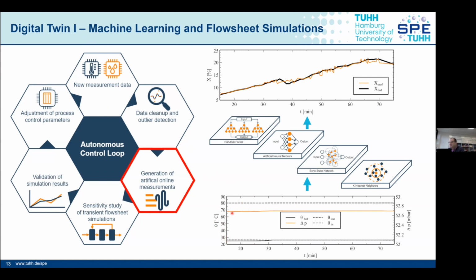Here you can see temperature distribution and pressure drop versus time, and with such artificial neural network approaches, we are able to predict then the moisture content versus time. As you can see here, this is a measured blue line, and the orange line gives us the prediction from this neural network approach. And that is fascinating. You can see in that particular case, we have an increase of the moisture content, which seems not very clear from the very constant values here, but which is very obvious for such an overweighting of the system. And this can be predicted.